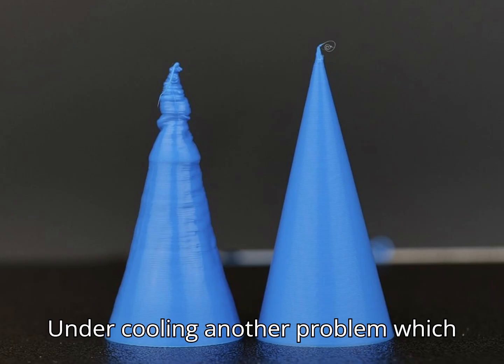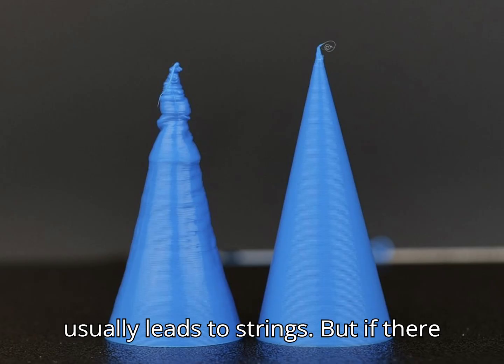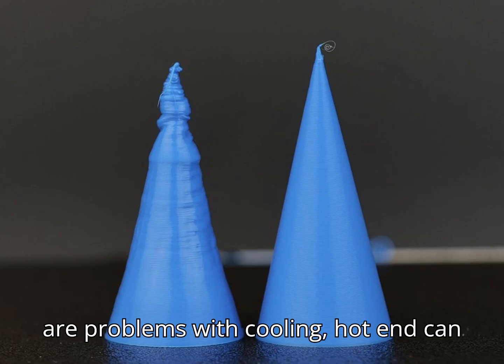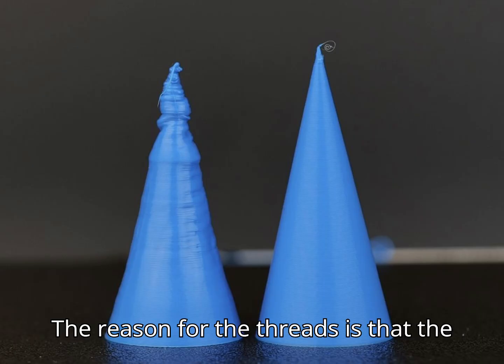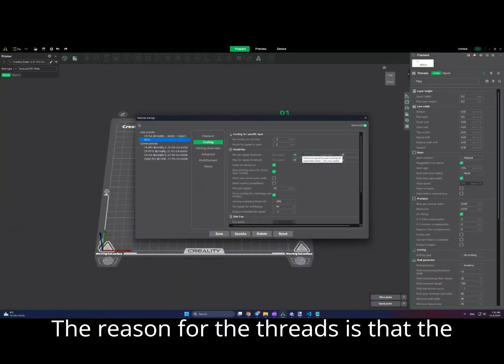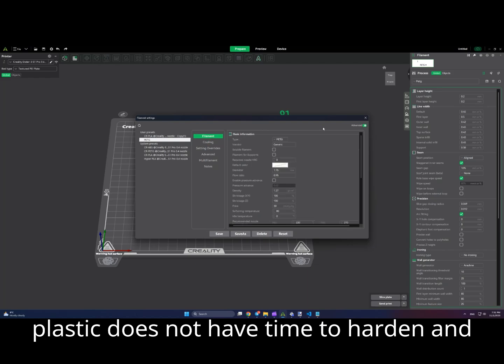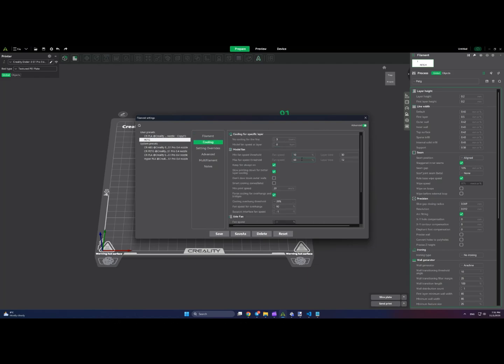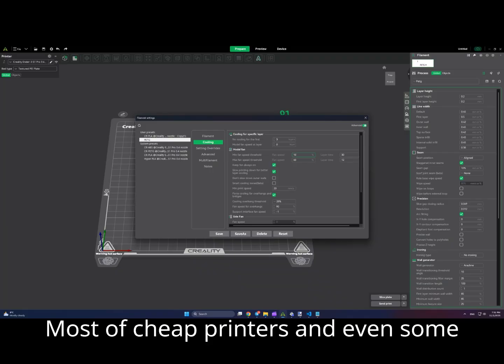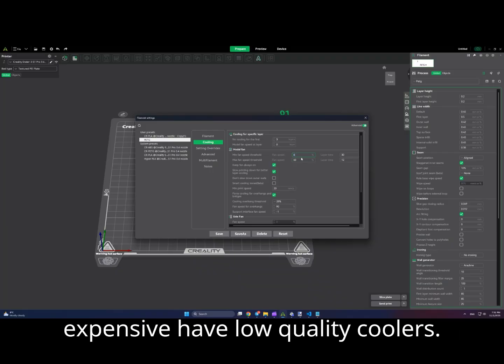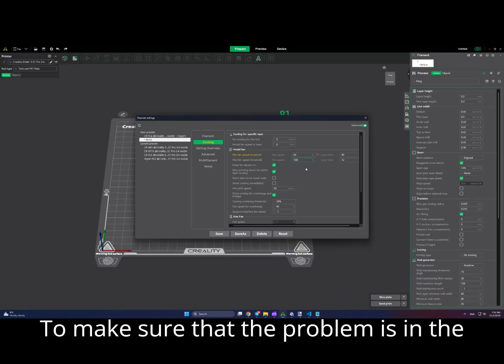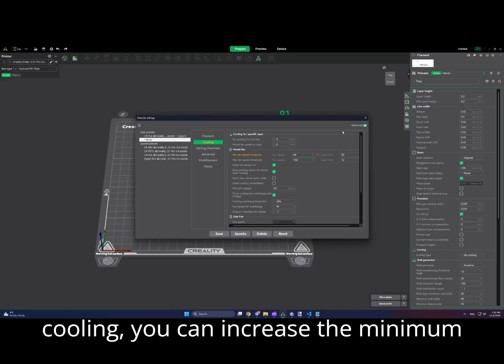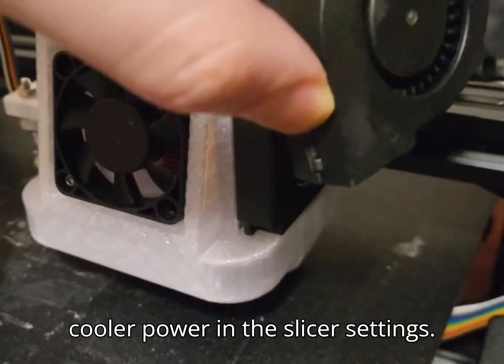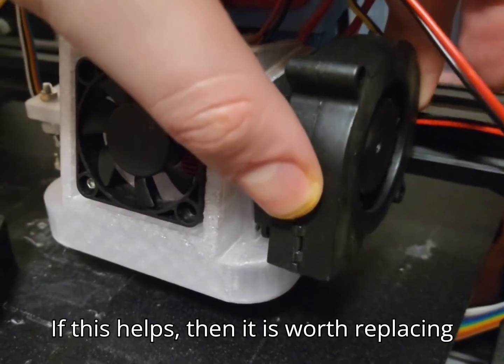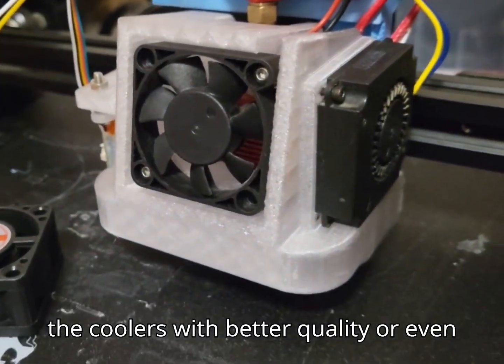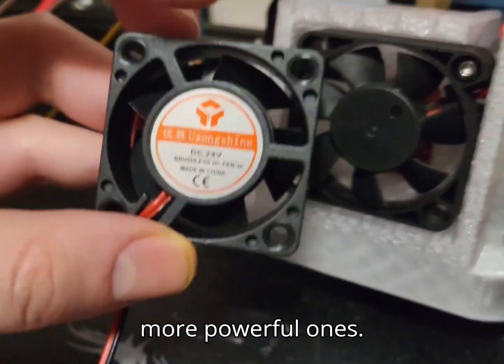Undercooling is another problem which usually leads to strings, but if there are problems with cooling the hot end, it can lead to blobbing. The reason for the threads is that the plastic does not have time to harden and remains partially attached to the nozzle. Most cheap printers, and even some expensive ones, have low-quality coolers. To make sure that the problem is in the cooling, you can increase the minimum cooler power in the slicer settings. If this helps, then it is worth replacing the coolers with better quality or even more powerful ones.